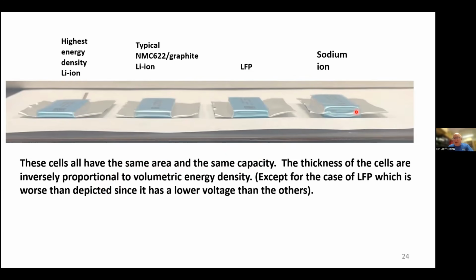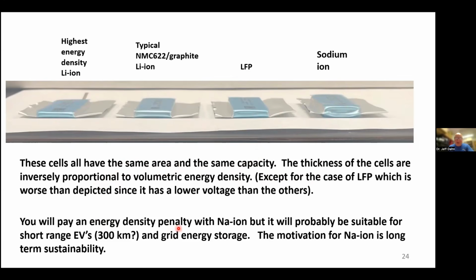So this sodium ion cell will have by far less volumetric energy density than the highest energy density lithium ion, at least a factor of 2 worse, and worse than LFP even. So what this means is, if you're going to use the sodium ion cell, you're going to pay an energy density penalty, but it will probably be suitable for short range electric vehicles like 300 kilometers, maybe 250, and it should be suitable for grid energy storage.